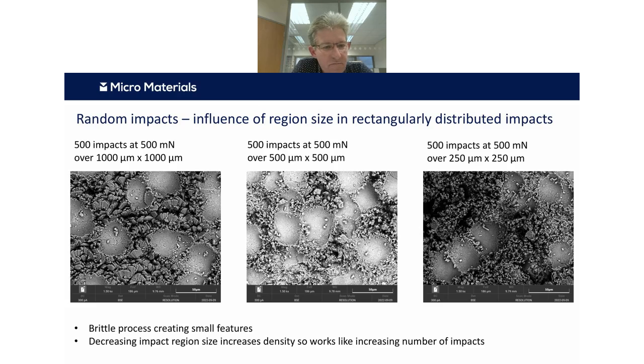And there we see really quite a dramatic evolution of the impact process, where this sort of columnar structure is completely broken up by these impacts. And so you're going from, on the left, you're seeing that columnar structure between the impacts, and in the middle it's starting to be broken up into much smaller pieces, and then on the right you're getting really this sort of filigree type structure. And you end up with a few of these compacted impacts in the end, but most of the original impacts are now being covered up by the debris. And that's not an entirely uncommon situation for an erosion scar, where essentially you're just seeing the result of the last few impacts.